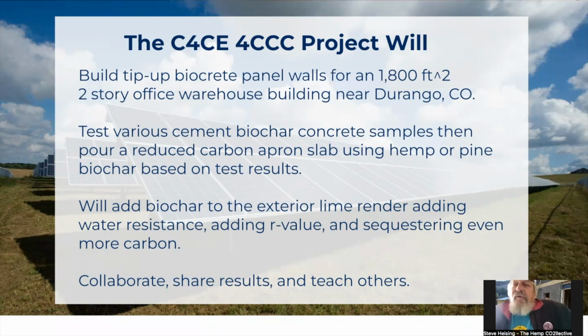So we're going to build a 2-story warehouse. We've done a couple of them before. We have been advancing a tip-up process where we lay down the 2x4 frame and then pour the hempcrete into the form, let it sit for 24 hours, tip it up, let it cure, start again.